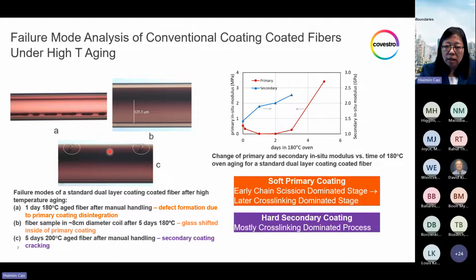This means the shift of the glass in this coil occurred in the first couple of days, and then it was fixed into this position with longer aging as the coating turned harder. I remember David discussed this with me after my talk at IWCS. If you do a test in the lab, for example a strip force test during high temperature aging, and you miss this early stage of the coating turning into a gel and wait several days, the strip force may seem normal and above spec, and you may think it was okay. But it was actually not okay, because you missed the point that with the coating already turned into gel, the strip force would have been way below your spec.